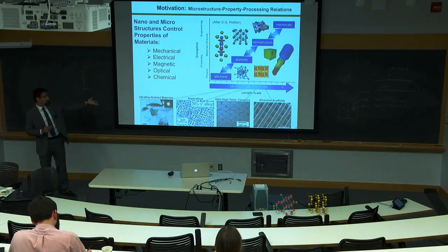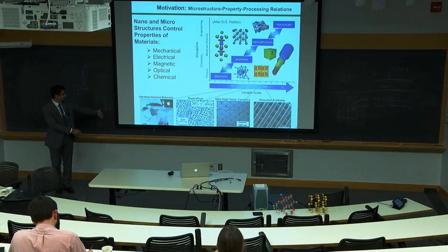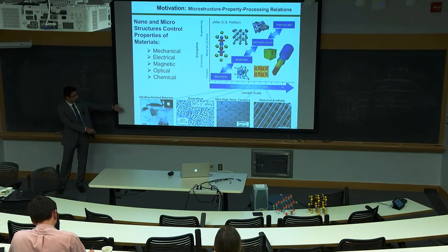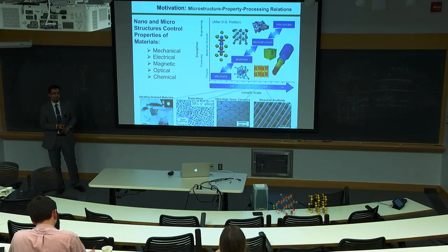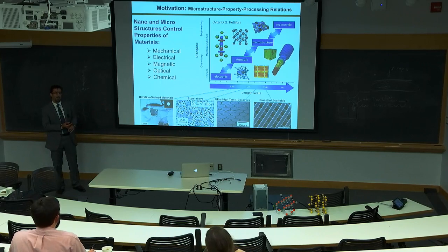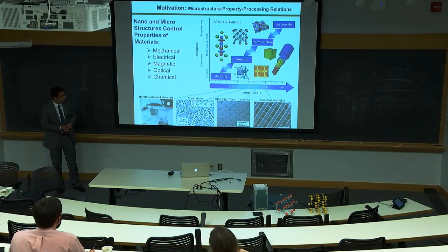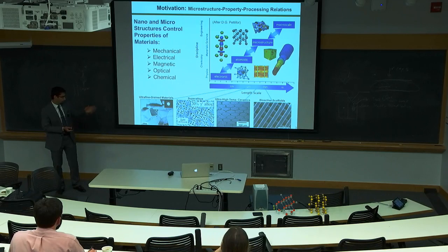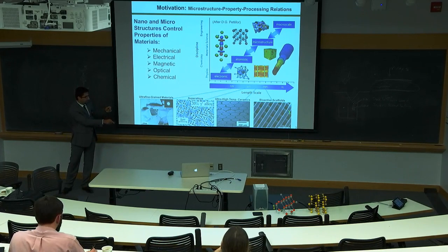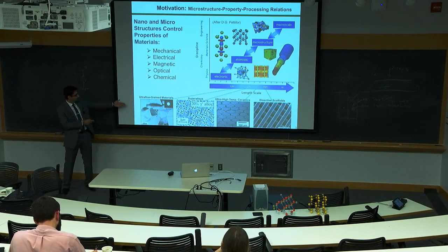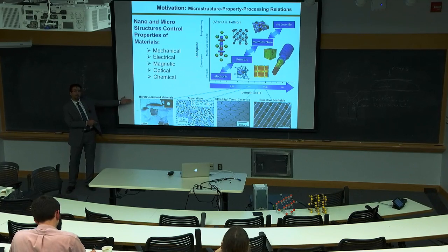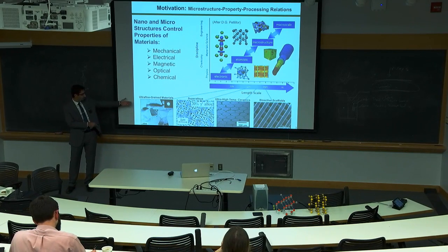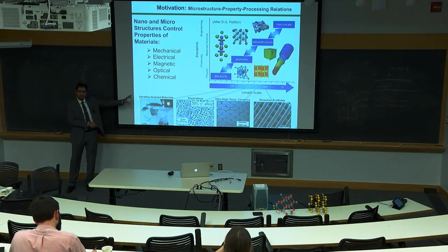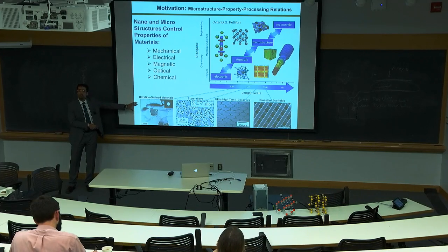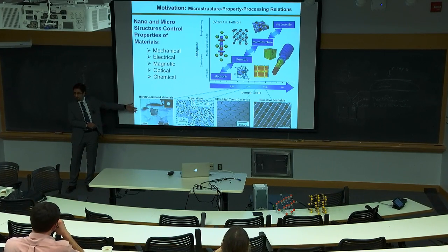I put these four pictures here. In the left, you see 100 nanometer length scale. In the right, you see 1 millimeter length scale. These are different examples that I have been working on, different projects. I'm going to shortly explain this one and this one because of time limit, but the first one is the ultra-fine grain materials, where the average grain size is about 100 nanometer. The grain size here determines the overall strength of the material.